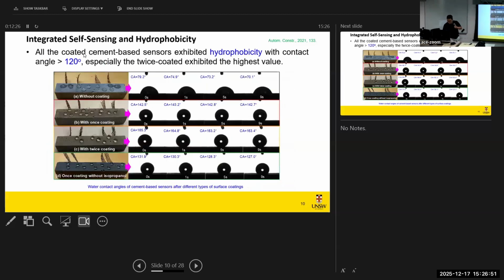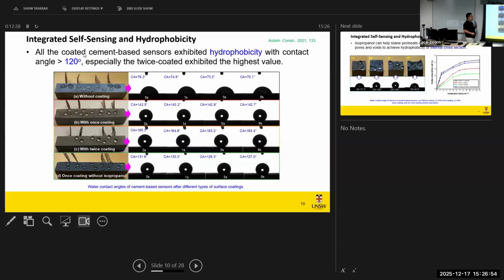And then let's look at the surface water contact angle of the different surface coating treatments. Basically, after surface coating treatment, most of the cement-based sensors exhibit hydrophobic behaviors, with water contact angle larger than 120 degrees. We also found that particularly the twice coated one exhibits the highest water contact angle. This is the water contact angle on the surface of the cement-based sensors, right?